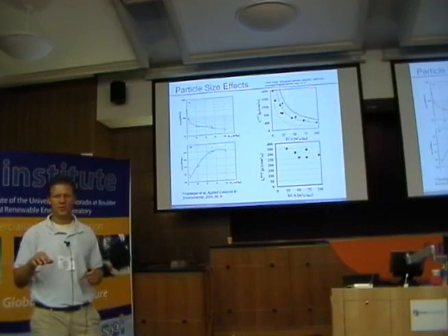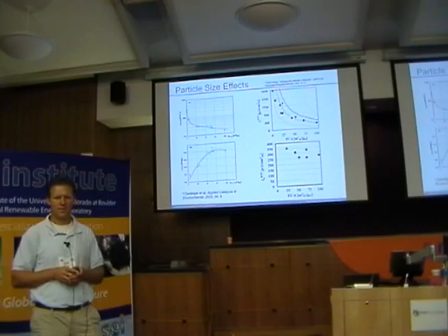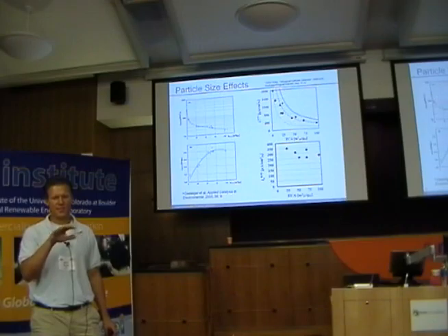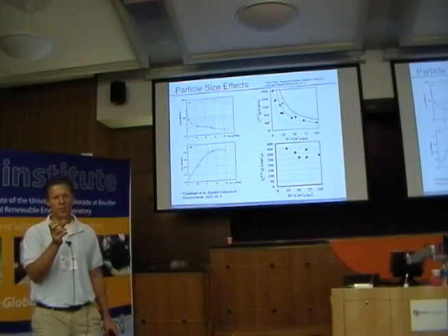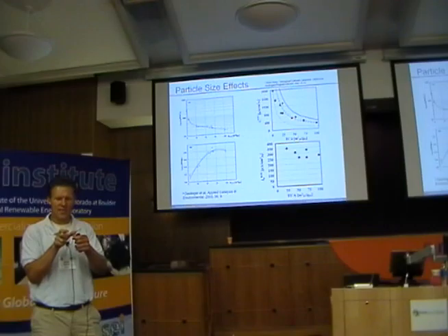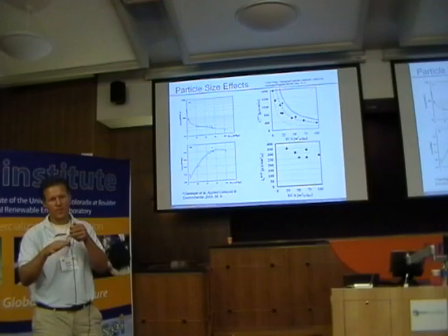Yeah, and it has to do with crystallography. Most of platinum, I think it's all FCC, a common crystal structure. So it's not because the crystal structure is changing, but when you look at the different faces, in 111, it's the most densely packed, and so the distance between each site is set. But when you go to 100, or you go to 110, then the distance between the sites changes.